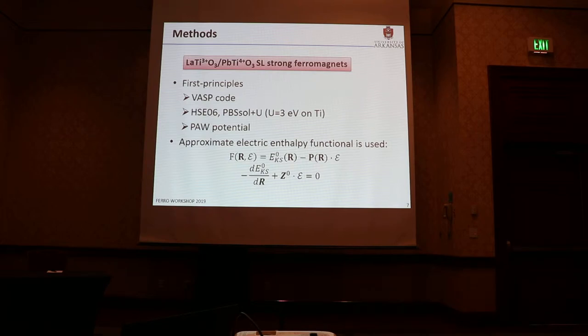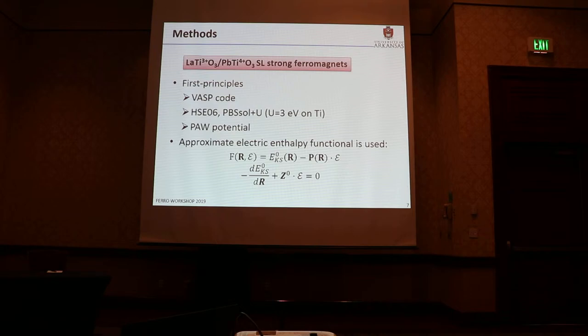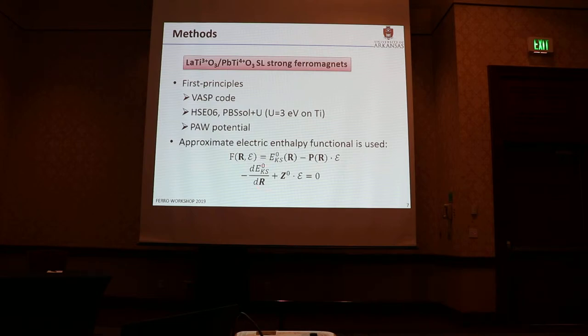We use the first principles method: HSE and PBEsol functional and PAW potential. We apply the electric field by this method. We use the approximate electric enthalpy functional, which is added by the polarization dot electric field, and the force on each atom is zero. This formula uses the Born effective charge and the electric field.